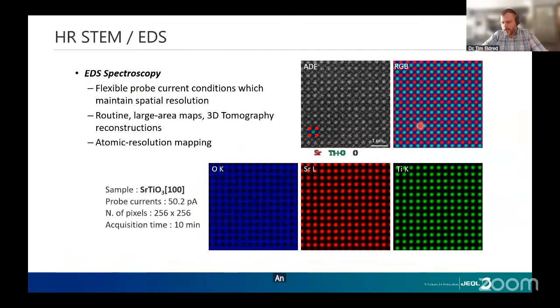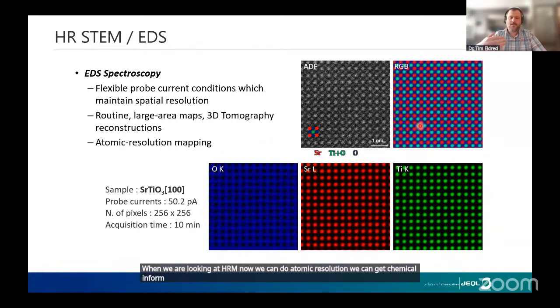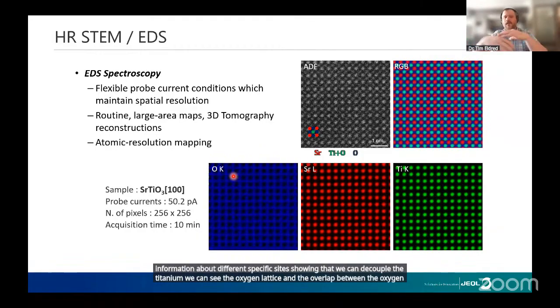I mentioned chemical mapping. When we're looking at it in HR STEM, now we can do atomic resolution EDS. We can get chemical information about different specific sites, showing that we can decouple the strontium signal from the titanium signal. We can see the oxygen lattice and the overlap between the oxygen and the titanium. And we can get all of this at very high resolution atomic data.